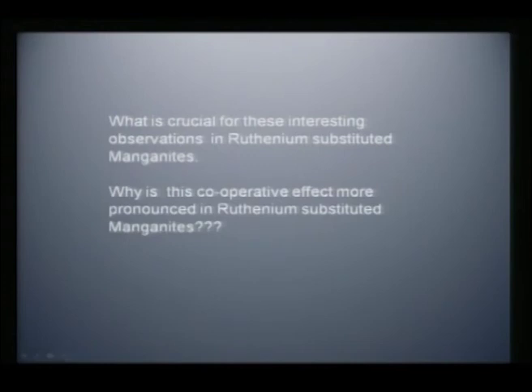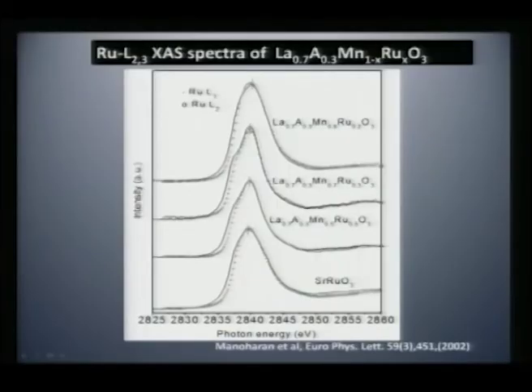So, what is crucial for these interesting observations in ruthenium substituted manganites? The next question we can ask, why is this cooperative effect more pronounced in ruthenium substituted manganites? Okay, these two questions we will try to understand from the spectra. This is an X-ray absorption spectra of ruthenium L2,3 edge, which shows there is a systematic change in the ruthenium edge when compared to SrRuO3, because SrRuO3 is supposed to be 4 plus, whereas in this case you would see the peak maxima shifting to the right side.